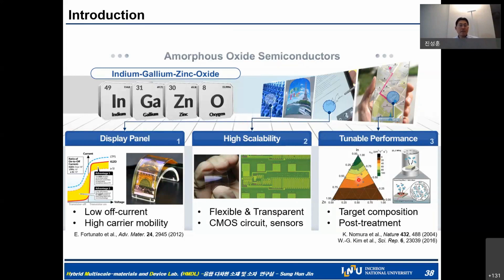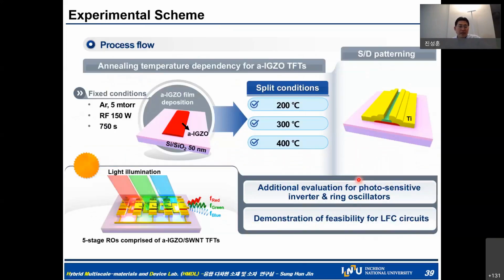With this kind of background, we intentionally controlled the photodetectivity by changing the annealing temperature, leading to different oxygen vacancy levels. Typically, most of the research has been focused on eliminating the oxygen vacancy completely. However, for the application of photodetectivity and frequency conversion circuits, we needed to secure, number one, relatively acceptable photosensitivity according to different wavelengths. Moreover, complementary circuit levels are necessary.